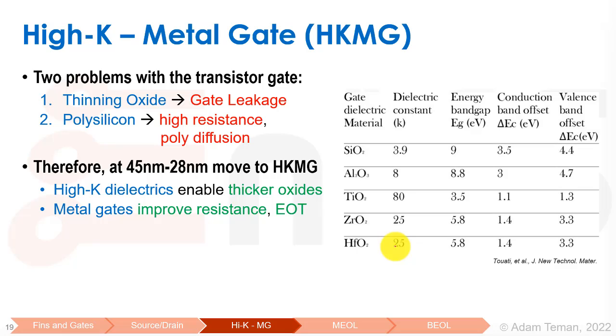And if we can have such a higher K, we can keep the same transconductance while using a thicker gate oxide, and we can reduce the gate leakage in that way. So we can continue oxide scaling to a point without getting a gate leakage that's too high. So that was one thing that we had.